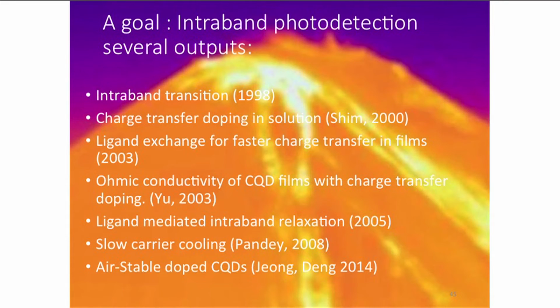Intraband photodetection was kind of the goal or vision that I had about 15 years ago of wanting to achieve, but it took a lot of time. First, we had to find that there was such a thing as an intraband transition. Then we had to solve the problem of putting charges, or doping the system, and we found a partial solution with charge transfer doping. Then we also had to make sure that we could get electrons flowing through a film of dots, and that led us to the ligand exchange, and then the ohmic conductivity. And then we had to understand this very fast electronic relaxation in those excited intraband states.